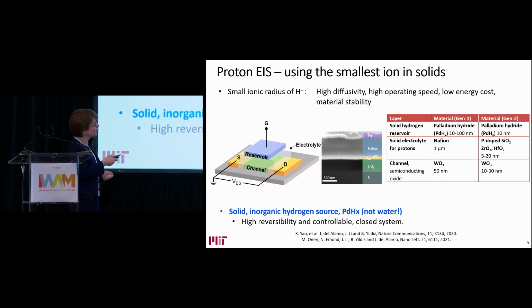And for this, we have adopted a metal hydride, for example, palladium hydride. Palladium likes to absorb hydrogen at large quantities, and it's still metallic, so this serves both as a closed system hydrogen source as well as the gate of the device that we want to control. For the channel, the target material, there are a number of binary oxides which intercalate small cations, such as tungsten oxide. I will show you others theoretically in a few minutes.